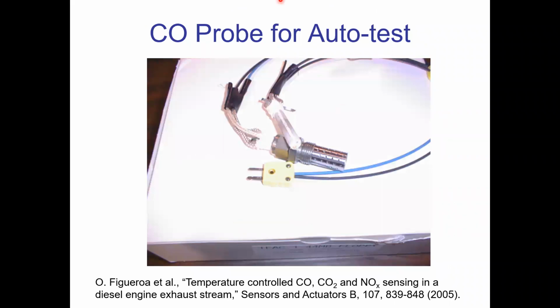There's another design where we put our sensor inside this stainless steel housing with holes. The gas would get access to the sensor through these holes. And in fact, in this publication, we find that we have made this type of probe for CO2 and NOx, and we have tested in this automotive sensor testing environment.